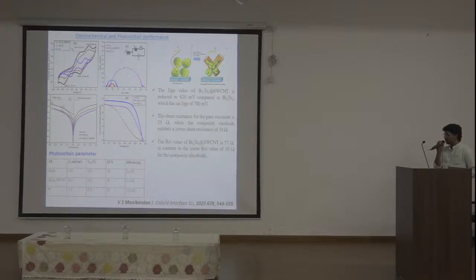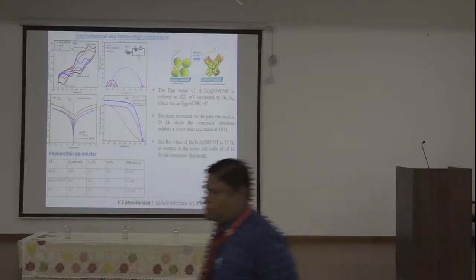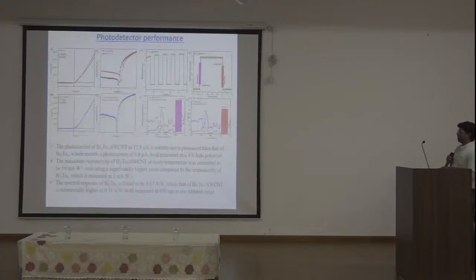So the bismuth telluride and CNT composition still gets less power conversion efficiency compared to platinum, but this is the first time we have checked how bismuth telluride's topological surface state is induced in this counter electrode application. Also, I'm not going to discuss this further, because I have already checked the same material for photodetector performance.